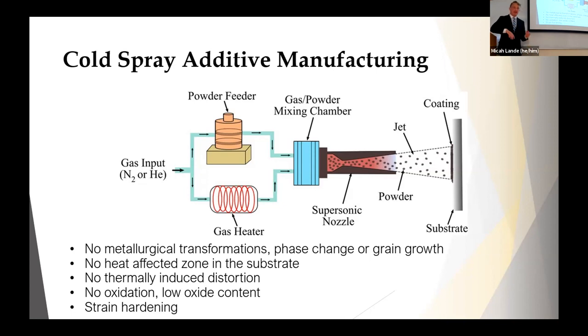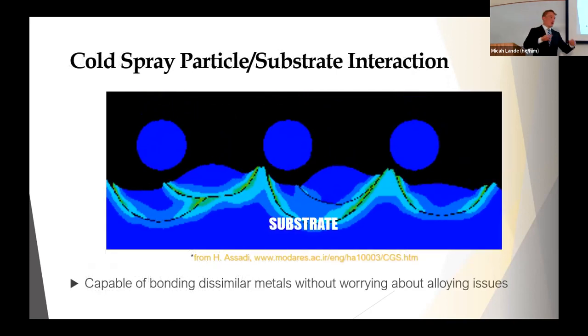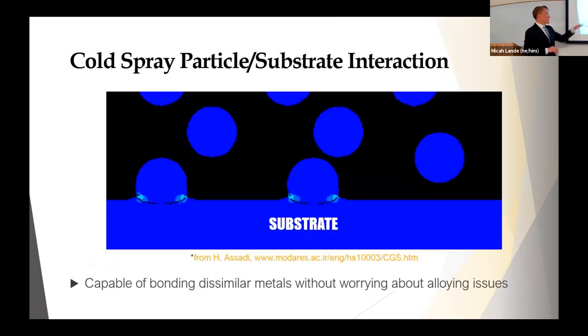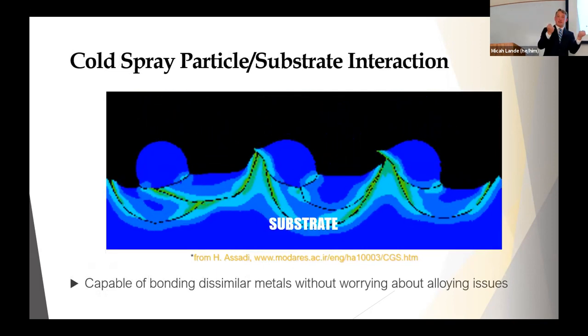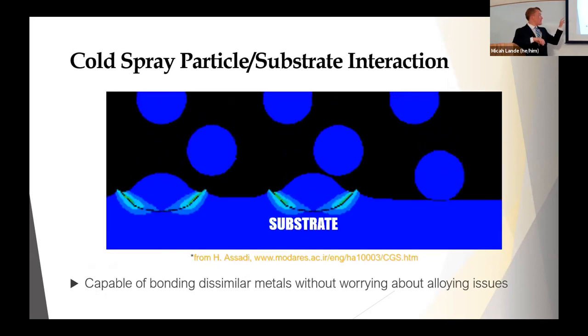And this has the benefit that we can bond almost any dissimilar materials. There are limits, of course, but you can very easily bond dissimilar materials, even to different substrates or surfaces that you wouldn't even think about normally, because none of these particles go through any kind of melting process. We don't have to worry about any kind of crystal matrix changes. We don't have to worry about any kind of oxidation or corrosion, because it's completely kinetic, where none of it is melted.